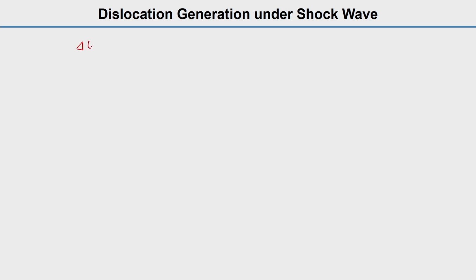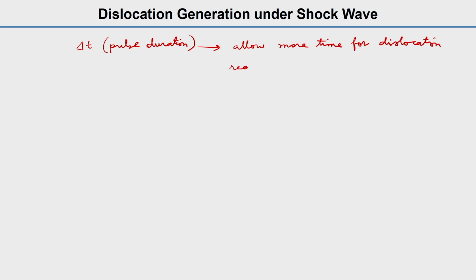also as we talked about, the delta T, shock pulse duration, also affects. So, what it does is it allows more time for dislocation reorganization. So, rather I would write higher delta T. Higher delta T will allow more time for dislocation reorganizations.